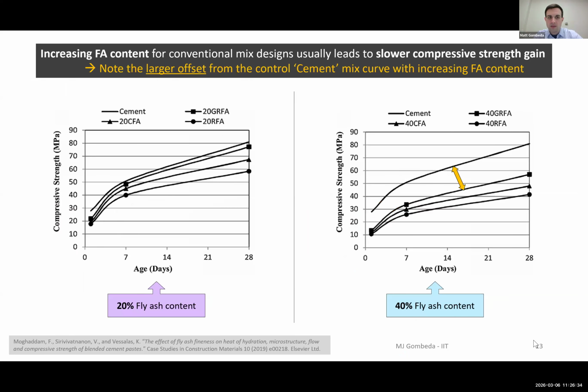And you can also see here the effect that another study that we did as part of a literature review, where that solid line on both curves is the control, it's the same mix. But when the dosage of the fly ash is going up from 20 to 40%, we see a significant reduction in the strength gain over the 0 to 28 days. But specifically in the early age window is where we're most concerned about, as we talked about earlier, which this study didn't even really zoom in on that area as much as we wanted to in our project.